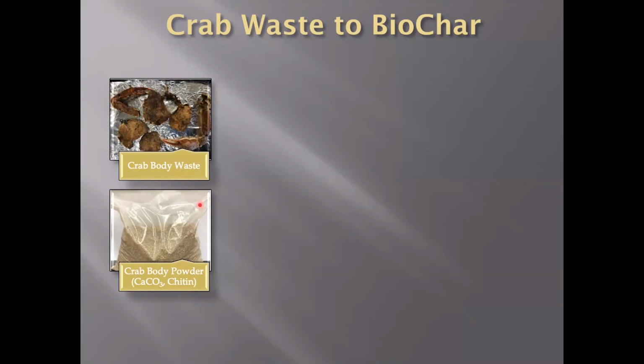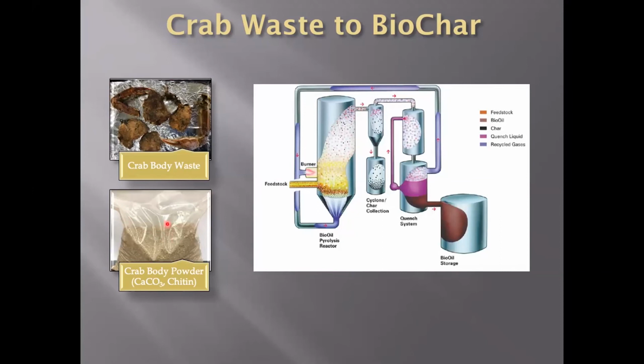But once we do dry the crab and grind it, we get this homogeneous material that you can see in this second image here in the baggie. It is a combination of a variety of whatever was in the crab waste that we got to begin with, but dried, but it's a much more homogeneous mixture. So it's largely calcium carbonate and chitin and other organics that would be found in the crab waste. But we have found that it's stable in airtight containers just at room temperature on the bench in the lab for up to 3 years. So it's fairly stabilizing as long as we're able to remove all the water from the crab waste when we receive it and dry it. Then we use this crab body powder as our starting material for the pyrolysis process.